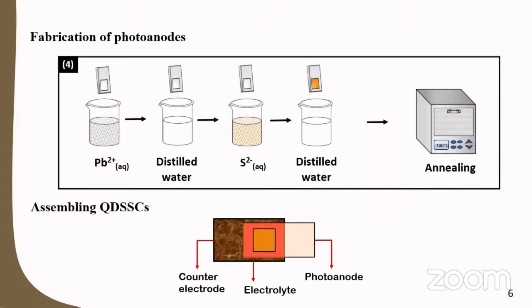Then, the prepared TiO2 electrodes were sensitized with PbS quantum dots using the successive ionic layer adsorption and reaction (SILAR) technique. The TiO2 photoanode was first dipped in an aqueous lead nitrate solution, followed by washing with distilled water, drying and dipping in an aqueous sodium sulfide solution, followed by again washing with distilled water. After a few cycles of this procedure, photoanodes were dried and heated at 100 degrees Celsius.